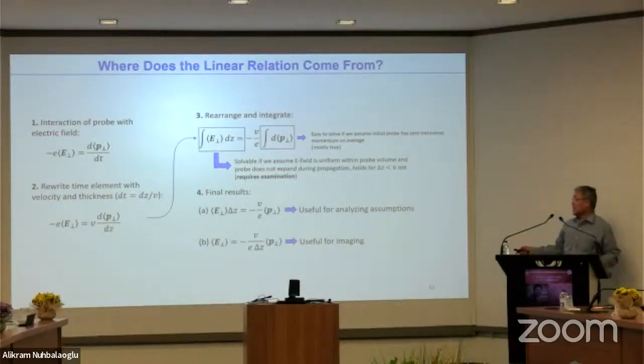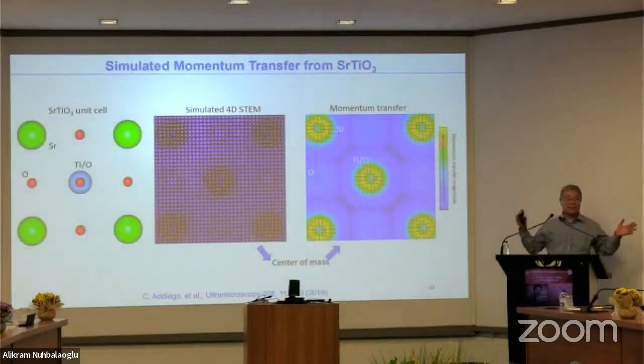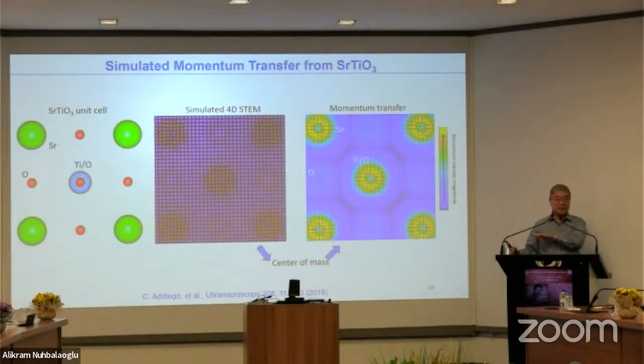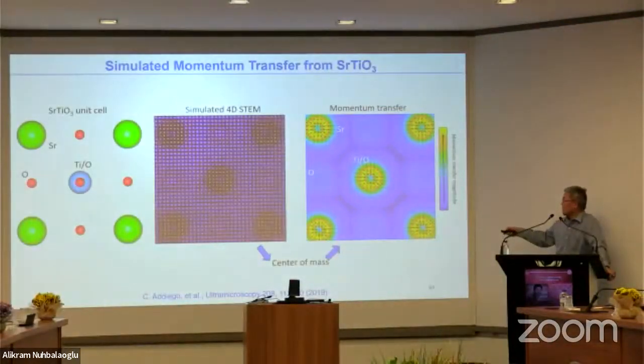So we did a detailed analysis. It turns out that for this particular example, the sample has to be 5 nanometers or thinner to stay near linearity. I'm not going into the detail, so that we know when these methods will be valid. With the electric field determined, you can use Gauss's law to determine the charge. I will show you in a future slide.